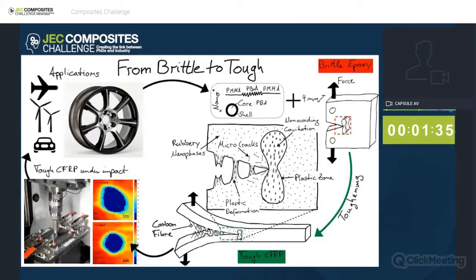In the next step, we transferred these macromolecules to the coupon level, where we had laminates included with carbon fibers. And what we found there, what was really interesting, is that due to the presence of the carbon fibers and the additional interfaces, we did not need a really long curing cycle anymore. The interfaces hindered the macrophase separation of these block copolymer macromolecular structures, and we generated nice nano-sized particulates throughout the whole epoxy system. The nano-sized structure is so relevant because it has a very high surface to volume ratio, right? And the more particles with a high surface you can put in there, the higher the likelihood that the crack can interact with those particles.